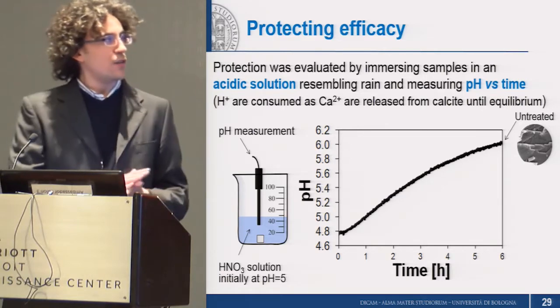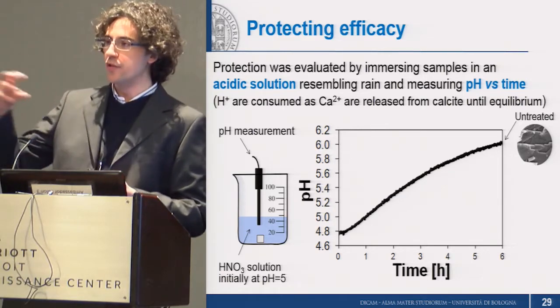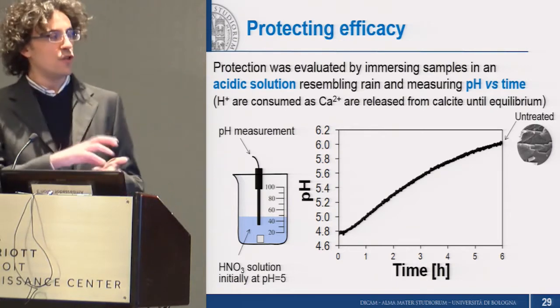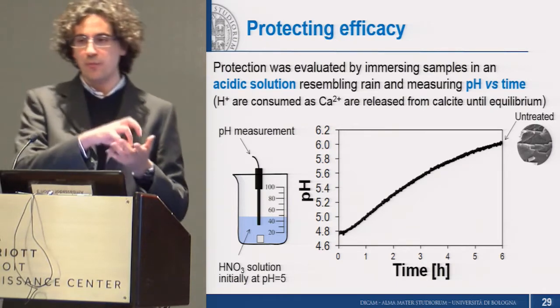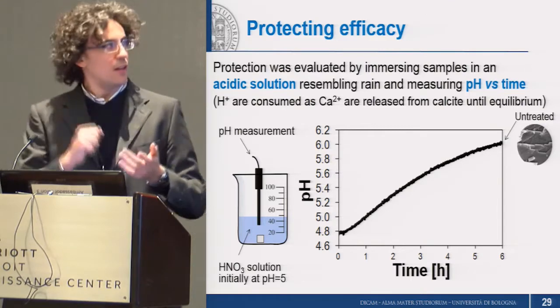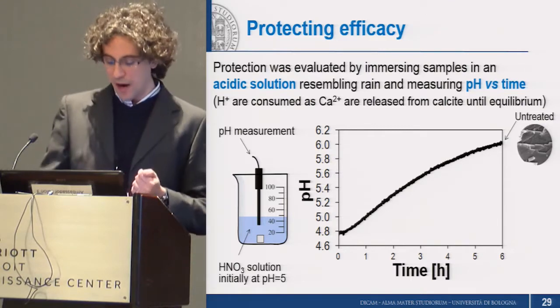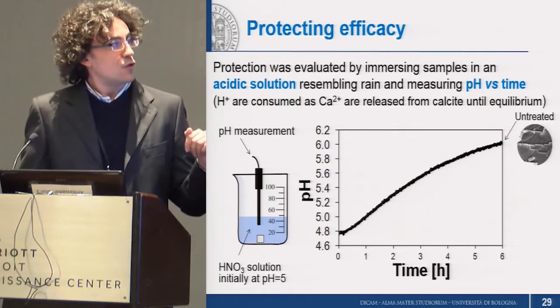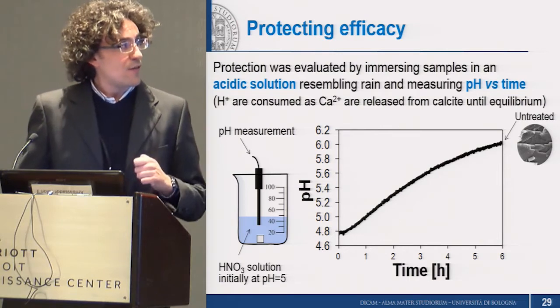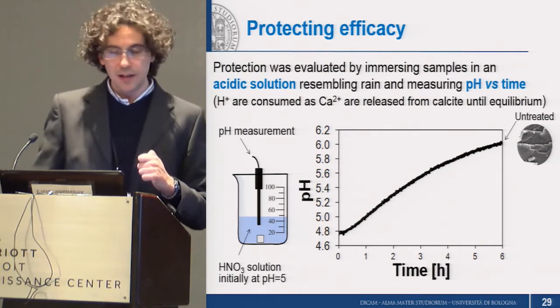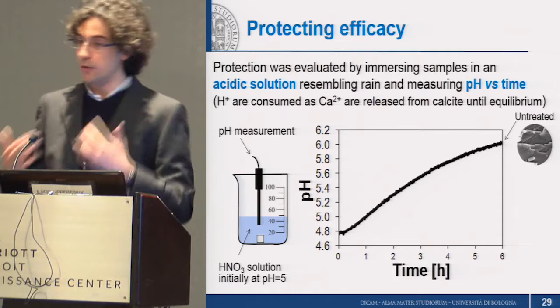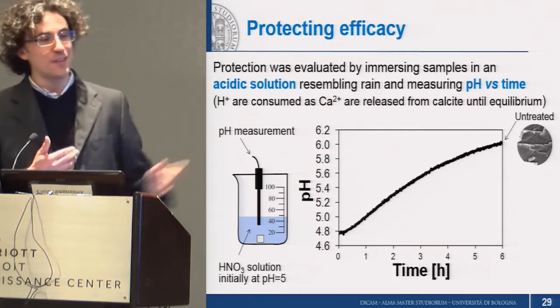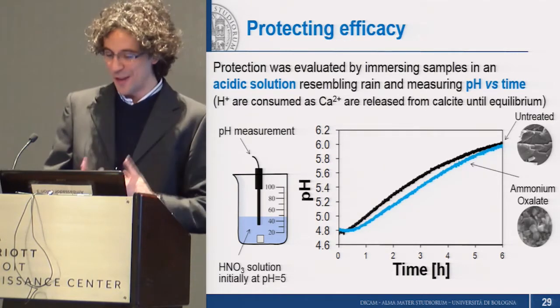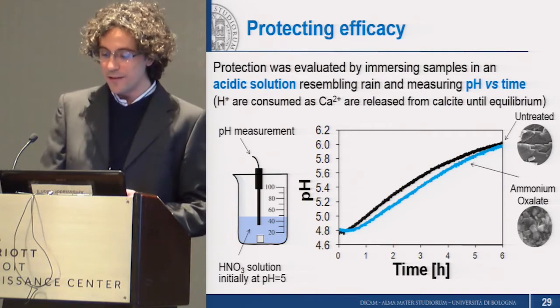As you can see in the case of the untreated samples, the pH increases over time because hydrogen ions are consumed as calcium ions are dissolved from marble. So this is the untreated sample. Then, as a reference, we tested ammonium oxalate, which is the commercial treatment, so nothing developed by us. And as you can see, the results were not so good. So we thought, okay, maybe we can do better.